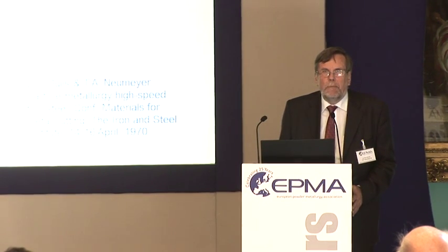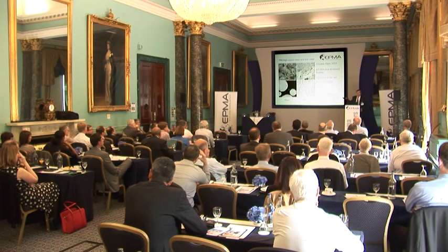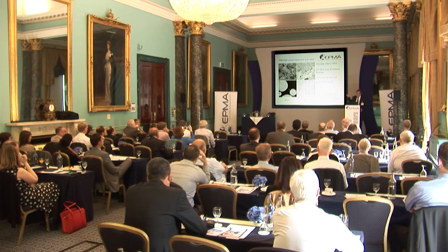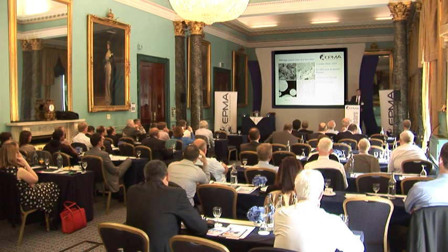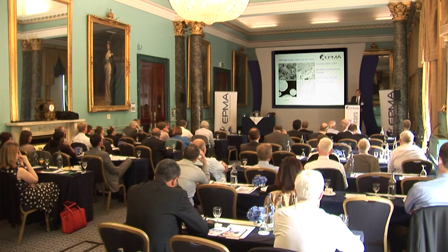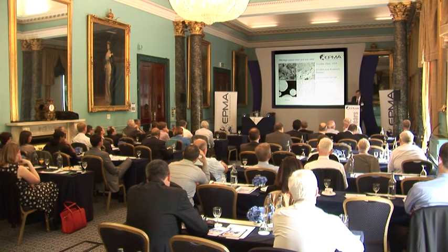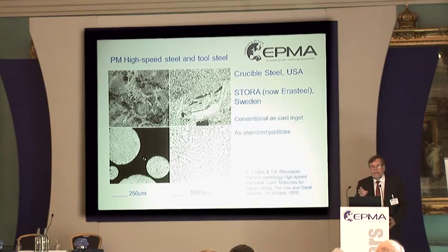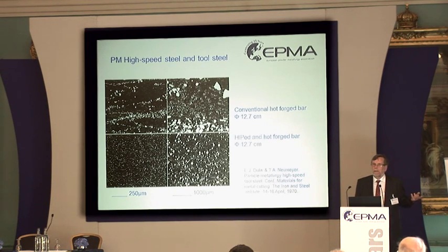This is an exciting area where there was initially a very severe competition between Crucible Steel in the USA and Stora, now Erasteel. On the top you can see the conventional cast structure, the carbide segregation in ingot cast high-speed steels, and you can compare it with the fine microstructure of the as-atomized particles. This was presented the first time in 1970 here in London at a conference arranged by the Iron and Steel Institute. The important thing is that by the HIP process, this fine structure is retained from the as-atomized powders.